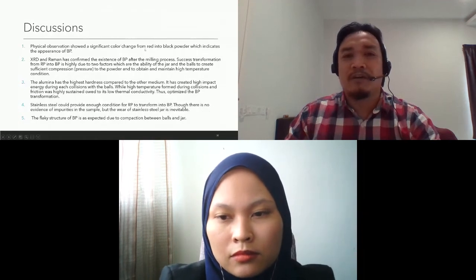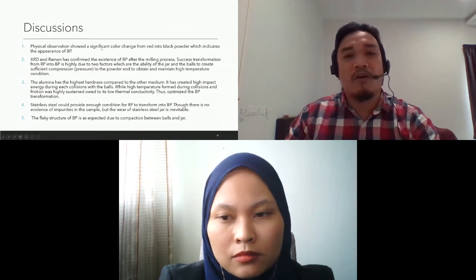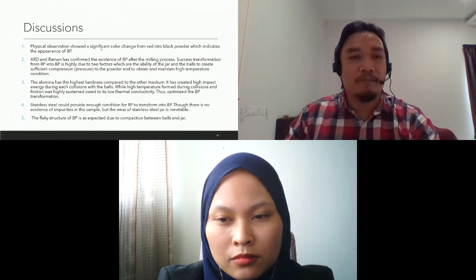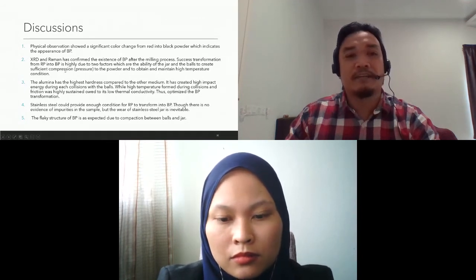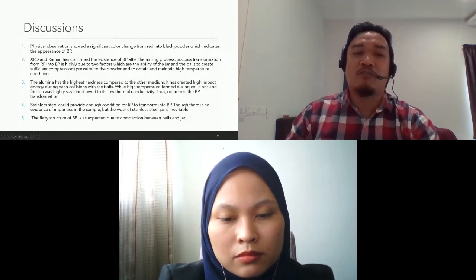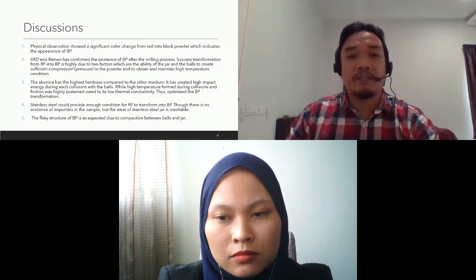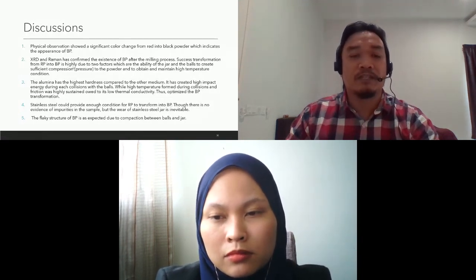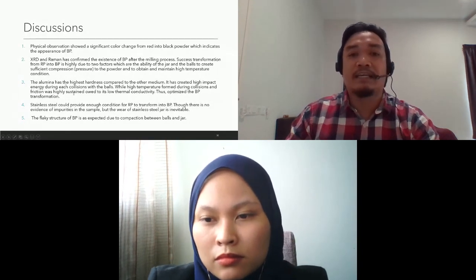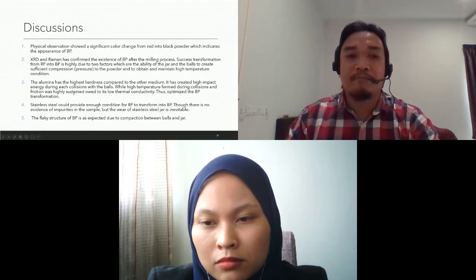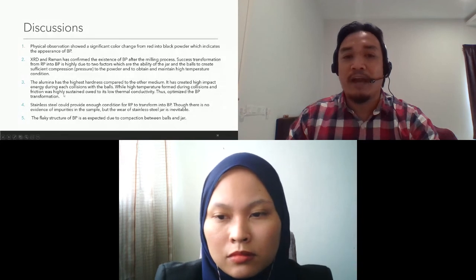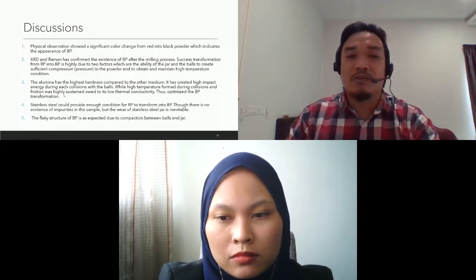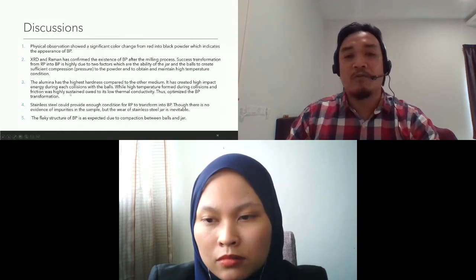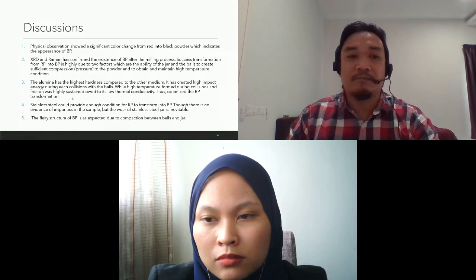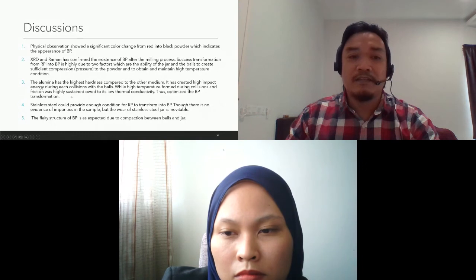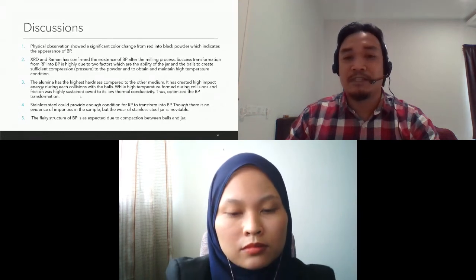In the discussion, from physical observation, the red turning into black powder indicates the appearance of BP. All the jars can give us BP from the RP, but from the XRD, we can say that alumina and stainless steel successfully yield pure BP compared to the granite. The alumina has the highest hardness compared to the other media. It creates high impact energy during each collision with the balls, and the high temperature formed during collisions and friction was highly sustained because alumina has low thermal conductivity, thus optimizing the BP transformation. And stainless steel could provide enough conditions for RP to transform into BP.